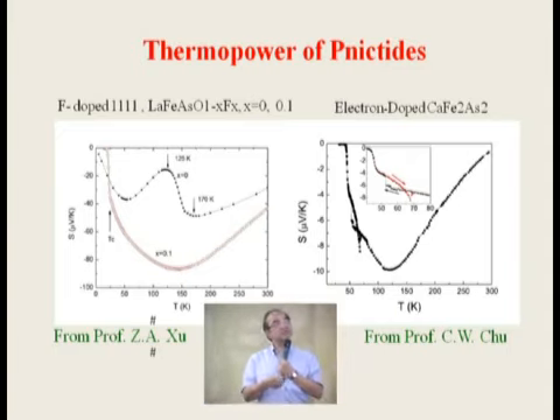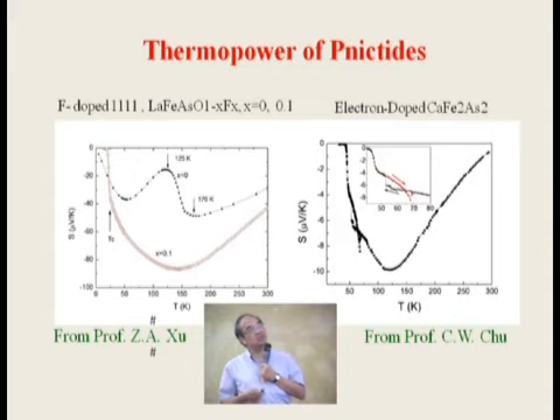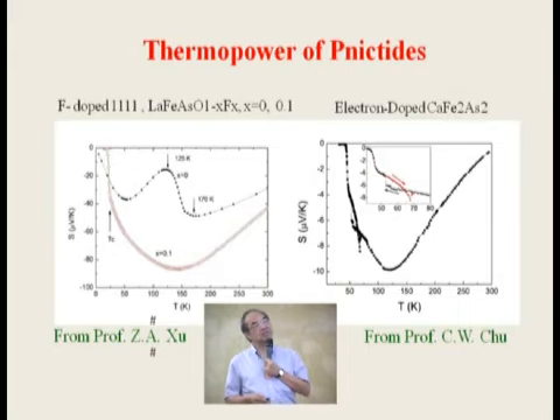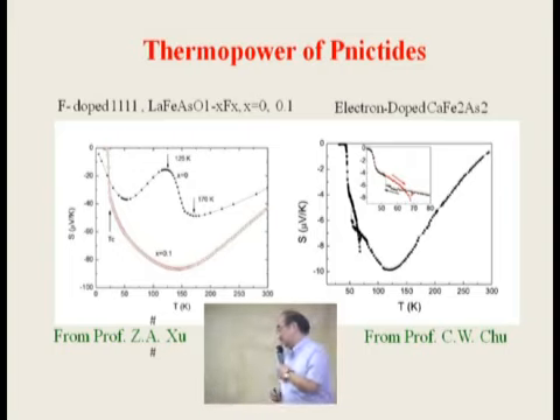And then just for comparison, we believe there are some general features for all the iron-based superconductors. This is data I got from my friend from China. It showed that the 1111 also has some kind of maximum in thermal power. And this is from Professor Chu. They were looking at this 122 compound, which is a superconductor. They also show that there is a maximum here. So this maximum thermal power will tell you something about this material.